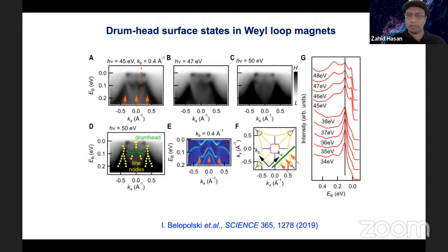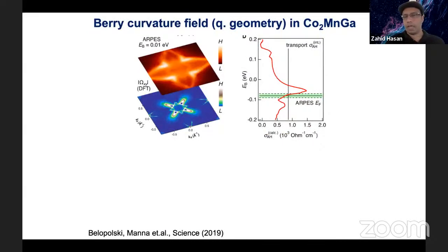Now I showed a lot of band structure mapping and a lot of spectroscopy. Why should you believe me in such a complicated system? So we developed a check: how do we know we did not miss a band somewhere? We took all these ARPES data and optimized the DFT prediction, and then used DFT to calculate the Berry curvature field distribution, or quantum geometry, of this sample. If you have quantum geometry in hand, then you can calculate transport, at least certain types related to ground state properties, for example anomalous Hall transport or quantum anomalous Hall transport. This was done by my postdoc, Guoqing Chang.